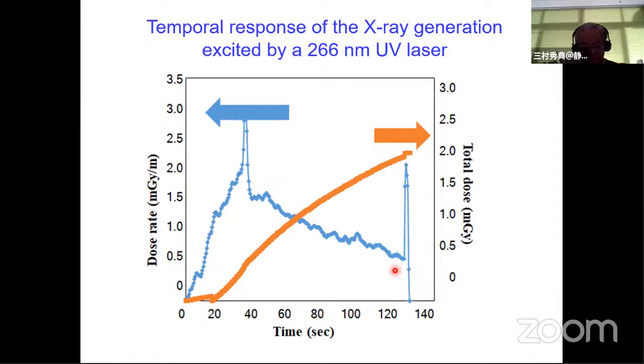This means the electron supply on the surface of the lithium niobate crystal is slower than the electron emission from the lithium niobate surface. So X-ray emission suddenly stopped due to the discharge.